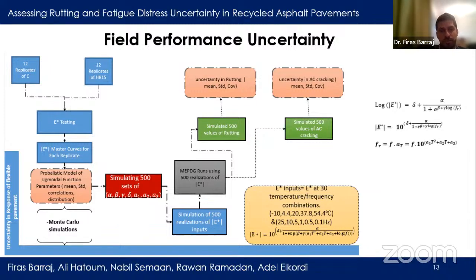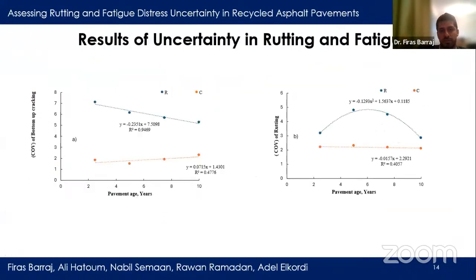Then a probabilistic model of the 7 model constants, which are alpha, beta, gamma, and delta, A1, A2, and A3, was developed to generate and compute 500 simulated values of the dynamic modulus E star for each type of the mix. In other words, for each of the 500 sets of these constants, we will obtain 500 simulated values of E star for the control and the RAP mixes. These 500 modulus values were then used in MEPDG simulation to quantify the uncertainty in the field pavement performance.